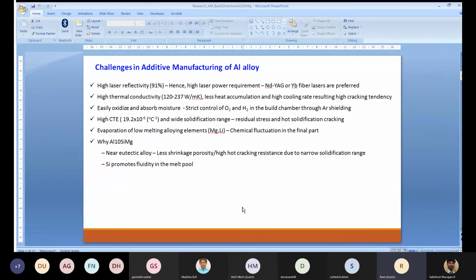Though aluminium has a low melting point, it is highly challenging to melt. The reason is it has a high reflectivity to laser, about 91%. Only 9% of the energy can be used for absorption and melting the powders. So high laser reflectivity dictates high laser power requirements. Again, in the type of laser, whether gas laser or fiber laser, fiber lasers of neodymium, yttrium, aluminum, garnet or ytterbium fibers are preferred, because these fibers' wavelength absorbability for aluminium is higher.